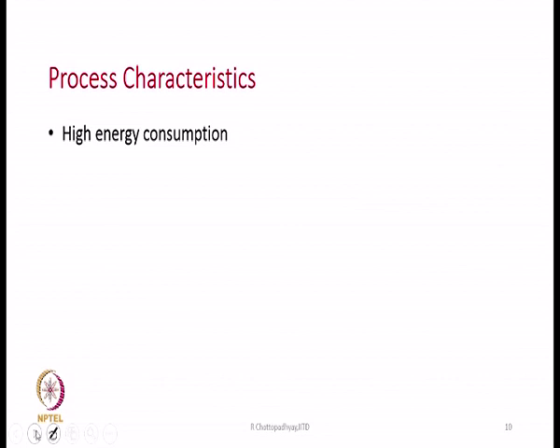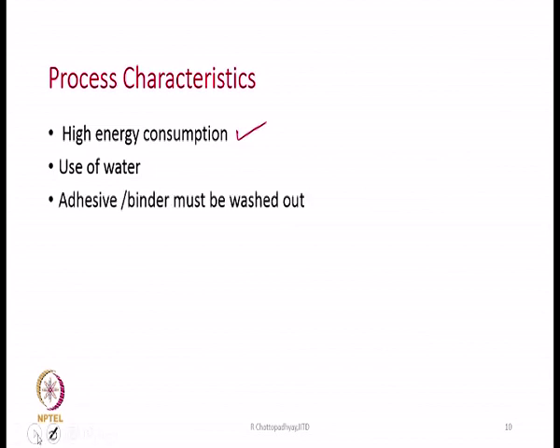Process characteristics, what is important is high energy consumption, because you have to have steam for the first twister that works with steam, and we need a dryer also. So, overall the power consumption is high. We have to use water also. We do not need any water in ring spinning, rotor spinning, jet spinning or vortex spinning, but here there is a requirement of water. And another important thing is, the adhesive or binder must be washed out completely. If it remains, the fabric will be stiff. So, washing out only happens after the fabric has been made.